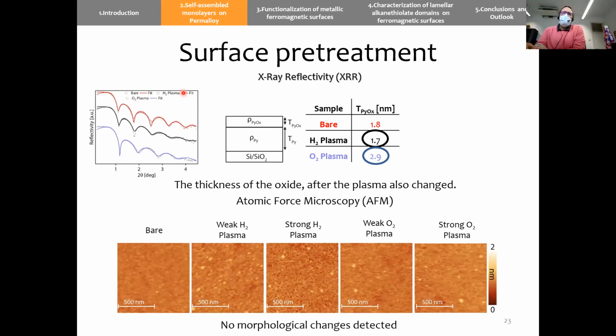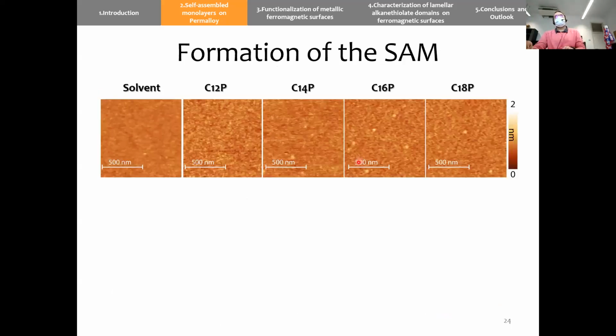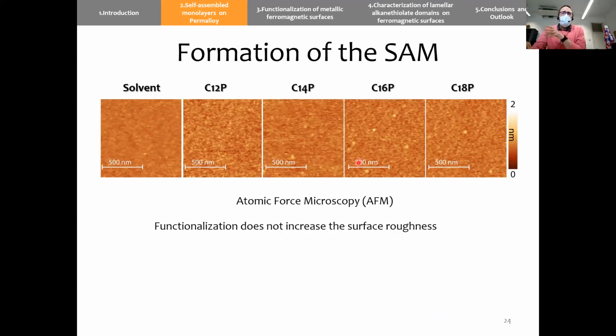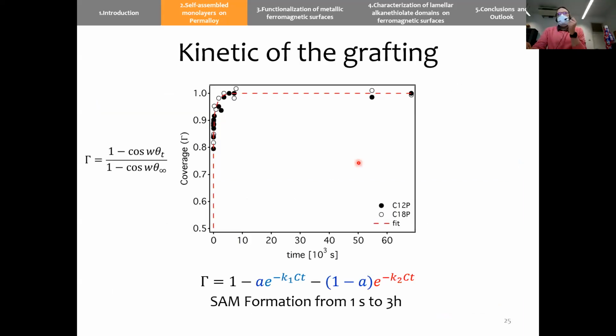By AFM we also checked that the roughness was not changing too much, and the thickness of the oxide also is not changing that much. When we form the SAM, we also see almost no changes in topography, and we don't observe an increase of the surface roughness. We also performed some kinetics, and we saw that these SAMs can be formed in 3 hours maximum, even though after 1,000 seconds we already have a quite stable surface.